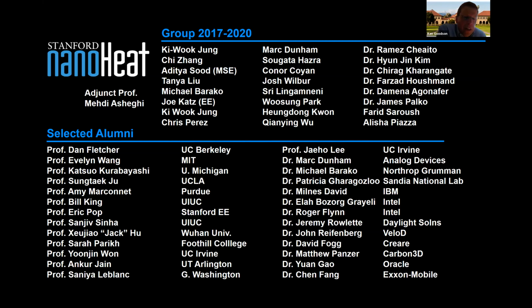Yoonjin Won worked on that. Amy Marconnet, who's now a professor at Purdue, worked on that. And that was all great, but we discovered that these carbon nanotubes and these low-dimensional structures are very, very delicate, and they get damaged very easily. So you would make a measurement and have a great result, and then after some cycling of the strain, you'd find that the conductivity wasn't as high. So they're very delicate materials. So integration of some of the 2D structures into practical systems is very, very tricky.